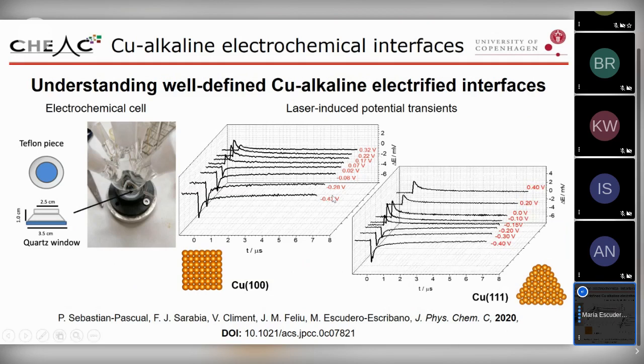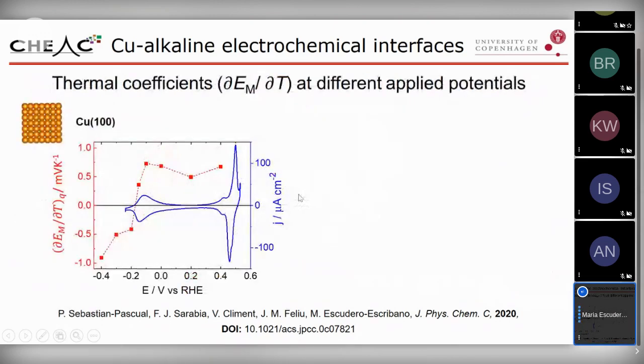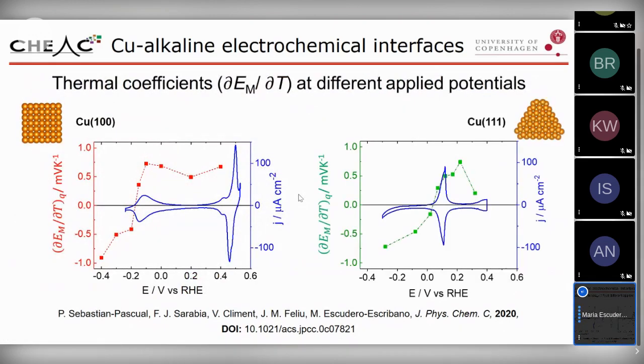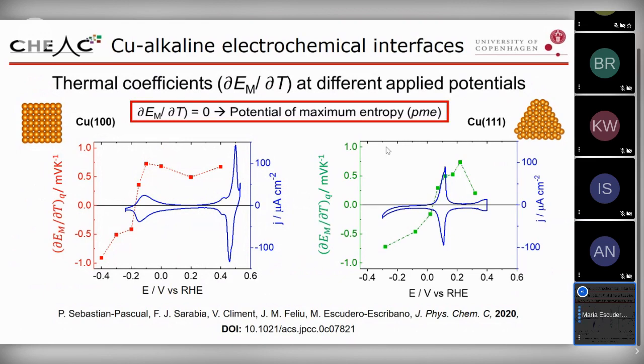And we can see the experiments that Paula and Francisco Sarabia led, done at different applied potentials. And as you can see, for both copper 100 and copper 111, there is a positive transient at positive potentials, and then the transient becomes negative. And just putting everything together, what this technique can give information about is the thermal coefficients at different applied potentials. This thermal coefficient is related to the potential of maximum entropy, and this gives information about the potential of zero charge. So these are the CVs that I showed before, and this is the thermal coefficient.